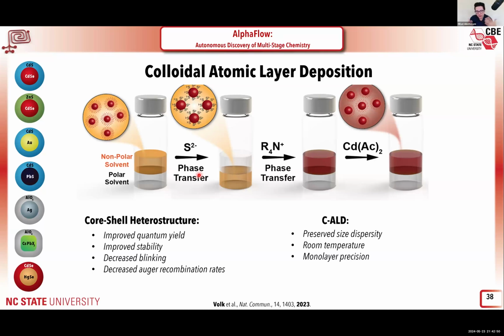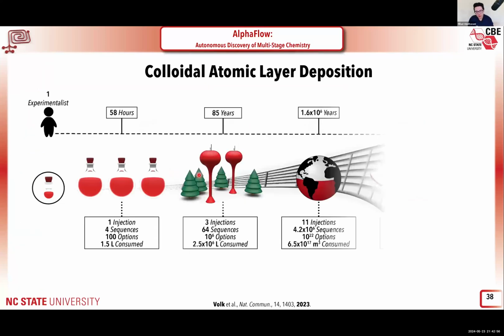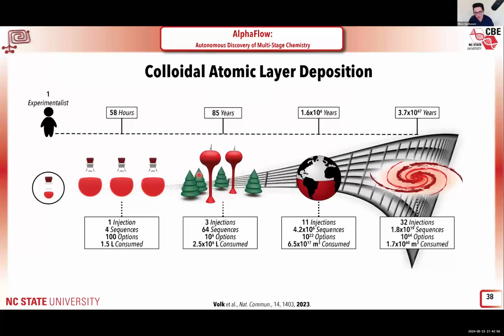The high dimensional space, as I said, can go up to 40 different dimensions that you have to tune. And if you want to explore this space, even just a partial grid search, if you want to do 5 cycles of colloidal ALD, you need about half of Earth's volume of precursor, because the process is just so high dimensional. If you want to do 10 cycles, you need a precursor volume equivalent to the Milky Way galaxy. That's why not a lot of people actually want to tackle this problem.